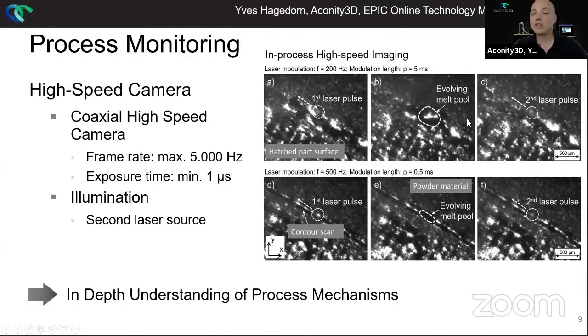And what you can do with that powerful tool is get an idea of what's happening, because typically the process is really, really fast and you don't see a lot. Once you get the possibility to see all that, you can change basic parameters like modulation frequency and the modulation length. And what you see here is the contour scan. Here's the laser again. The evolving melt pool is a lot smaller here than on the bottom or on the top. So that allows you to do fast material changes, fast material development.